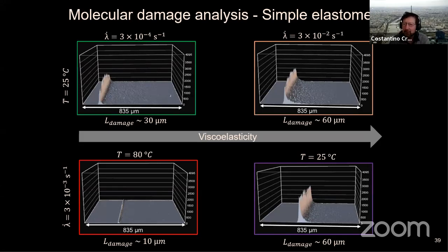Now, if you are thinking of the bond itself, this is a little surprising because bonds have a higher chance to break at higher temperature. So if you pull on the chemical bond itself, you would expect it to break a little bit sooner at higher temperature. But here in this experiment, we see much less bond breakage at higher temperature. The quantification, I'm just showing one slide.